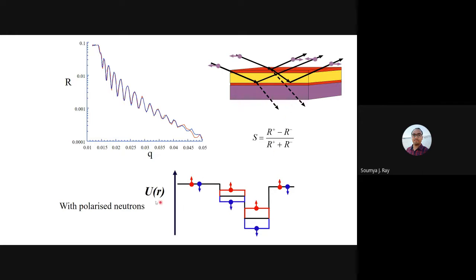So as a result, if the neutrons are polarized, that means there will be up and down neutrons. Then they will experience a difference in the potential for the two types of neutrons. For example, if the bottom layer is non-magnetic, then there will be no difference in the potential experienced by them. However, if there is a magnetic layer, then these red neutrons will have a slightly higher potential and the blue ones will have slightly lower. If the next layer is more magnetic, then the contrast will be even more, and so on.